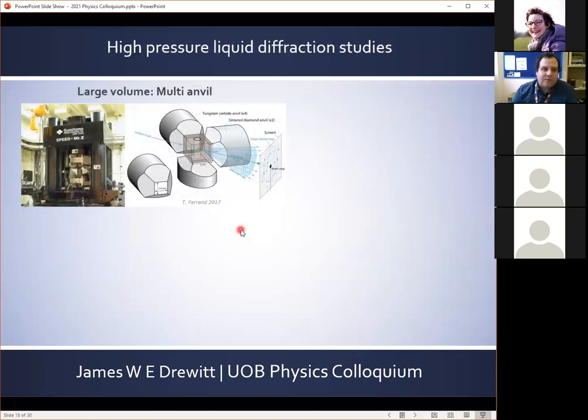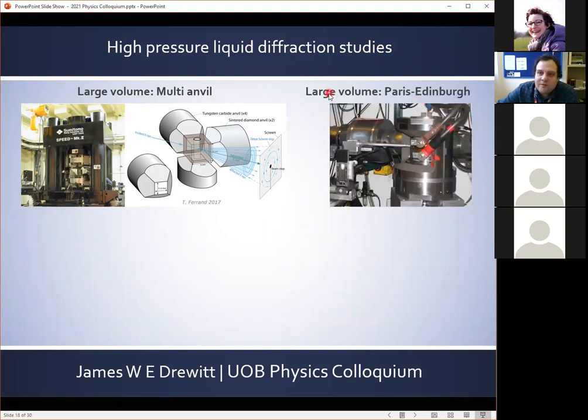Okay, so moving on from ambient pressure liquid diffraction measurements, I'm going to talk about some high pressure liquid diffraction measurements. As mentioned earlier, there are several ways to generate high pressure conditions to measure, and early structural measurements of liquid at high pressure used large volume multi-anvil techniques with energy dispersive X-ray diffraction to mitigate the fact that we have very limited scattering angle accessibility, due to these huge multi-anvils which get in the way of the scattered beam. Another large volume technique using a Paris-Edinburgh press was developed to optimize the scattering angle accessibility, and actually this has been successfully applied with resistive heaters to measure liquid structures at high pressure with synchrotron X-ray diffraction.